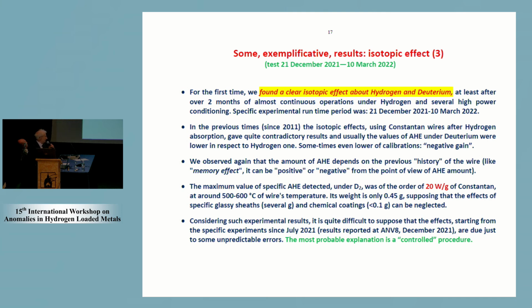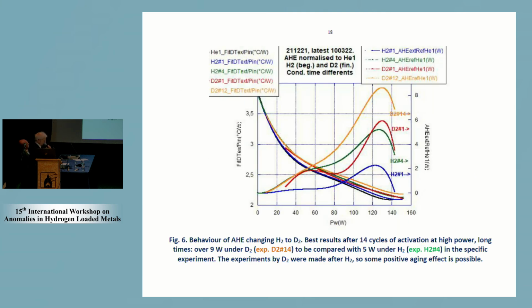So after 1 day, 2 days, we moved to another kind of experiment. But the point is, at the time, we didn't wait long enough. We wanted to get a new result as soon as possible, so we didn't wait enough time under deuterium. This time we waited enough, the experiment of December, 3 months.